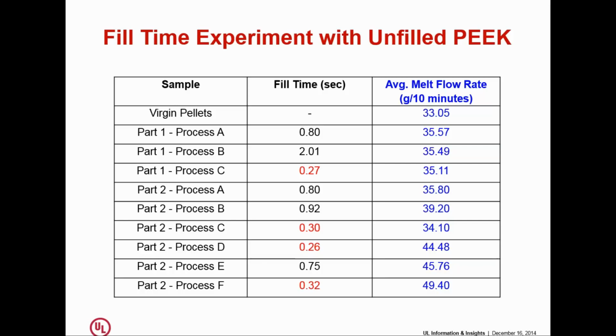Same thing happened with part number 2. Now you notice that these 3 processes, D, E, and F, develop a much higher melt flow rate than A, B, and C. What did we do here? We raised the temperature of the barrel in order to be able to slow down the speed. And this is where we actually did the damage to the material. Not that this is damage. This is still acceptable, but it's marginal. So it's a good illustration of the dual role of temperature and shear on how a material is truly influenced. You have to really put numbers to this and not just engage in a lot of mythology. And there's a lot of mythology out there in our industry.